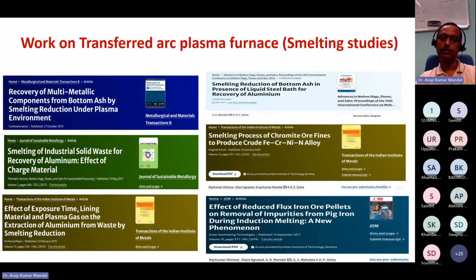We have prepared the crude stainless steel from the chromite ore fines to make the iron, chromium, nickel, nitrogen alloy, where the nitrogen can somehow replace the nickel. Therefore, directly you can get austenitic stainless steel, nitrogen bearing stainless steel, if you use the nitrogen plasma, okay. We have also done some experiments, not in plasma, but using this furnace as an arc furnace to remove the different impurities by using high flux DRI in this electric arc furnace.